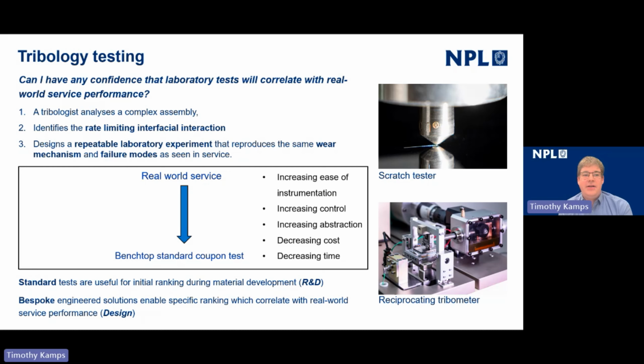The first one is to understand how the surfaces that are experiencing relative motion interact with each other. So this is analysing the complex assembly. Quite often there may be secondary motions occurring superimposed on top of the primary motion, and these may actually be the cause of the failure or unexpected lifetime of a component. The second part is to identify the rate-limiting interfacial interaction. When we look at this, we're looking at the condition where the power that we're dissipating in that contact is beyond the wear mechanism that we're expecting it to operate in, such as the transition from mild abrasive wear to adhesive wear.